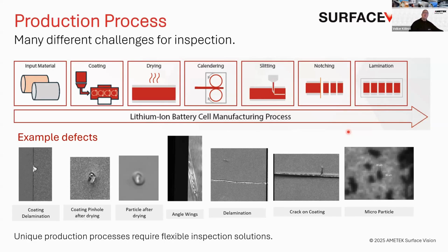And since the separator, which is the layer between the anode and the cathode, becomes thinner and thinner, so maybe today it's between 9 and maybe 12, 13 microns. Depends a little bit also on the end battery. I'm talking more about the automotive battery here. But if you have particles, they are bigger than 10 or 20 microns, and they're hard enough, they can penetrate the separator, and this can cause then shortages, and you get then a heat zone there. And this could then also lead to a bad quality. And in the worst case, on the lithium-ion process, this could also be a safety issue in terms of thermal runaways, for example.